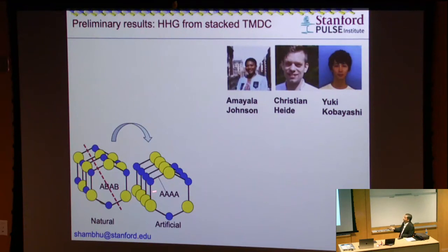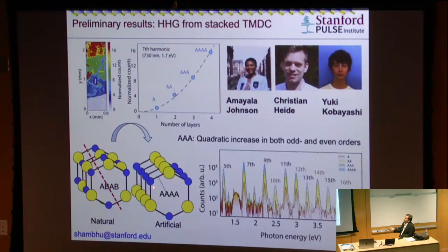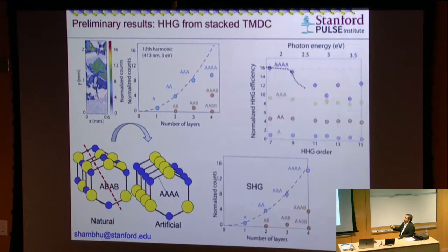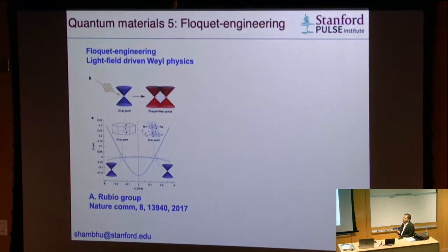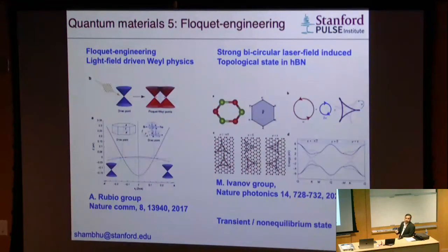Okay. So in this arrangement, these are the actual people who did these nice things. And when we do this in the same arrangement, when you line up these atoms, which is called the AAA configuration, what we find is that the harmonic intensity actually increases as a function of the number of layers quadratically, as expected. Okay, so optics makes sense, right? I think this is just our first step to get a handle on various numbers of layers, and eventually we want to reach the Moiré physics. Make this interesting material science problem into also an interesting optical science problem, if you like. And just finally, there are some interesting theoretical predictions that we could test, which are on creating and controlling novel quantum mechanical states in interesting materials.